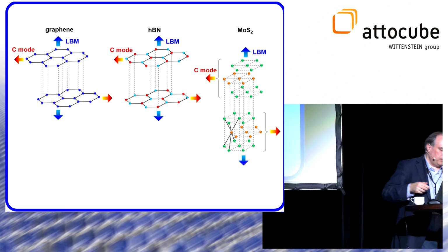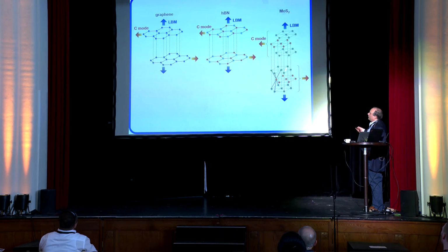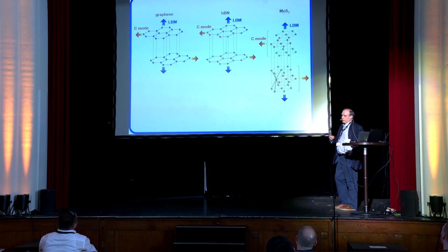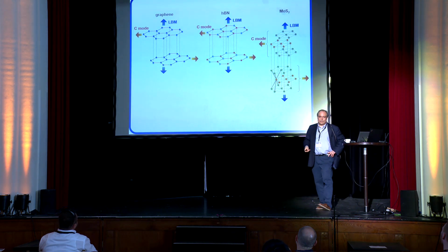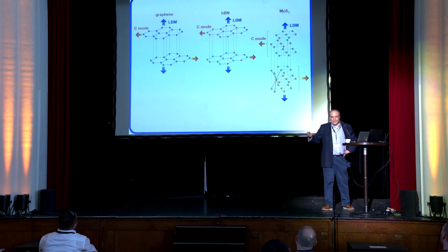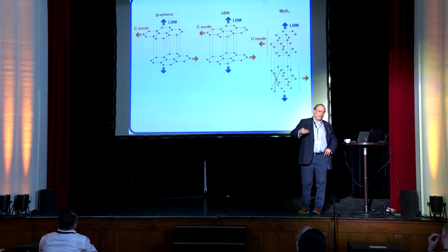So bottom line, what we showed a couple of years ago, is that all the layered materials, whatever they are, they can be MoS2 or hBN, graphene, you can do like in these jokes about physicists, that you can model all of them as a ball and a stick, and that's good enough. And you can do it really because it is good enough, the ball and the stick, because the in-plane interaction is so much bigger than the van der Waals interaction that the joke about the physicist and the ball on the stick perfectly works here.